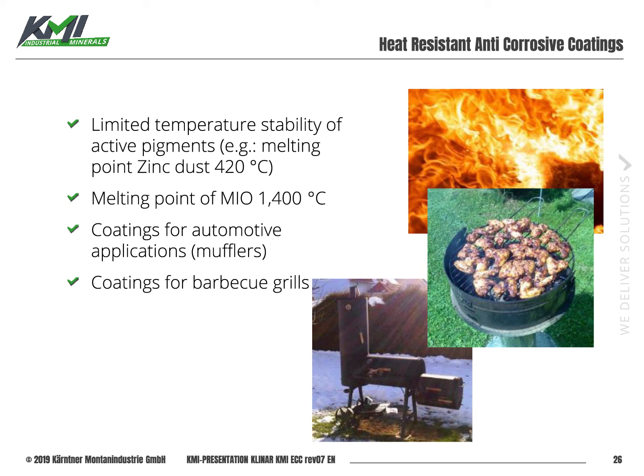Micaceous iron oxide, although it's only a passive barrier pigment, when you use one of the finer micronized grades, for example Micro 15 or Micro 10, you can create quite reasonable corrosion protection without any active pigments, because there are the limitations. For example, the melting point of zinc dust is 420 degrees C. You can have some heat stabilized zinc dusts withstand a little bit higher temperature, but far away from 1400 degrees.